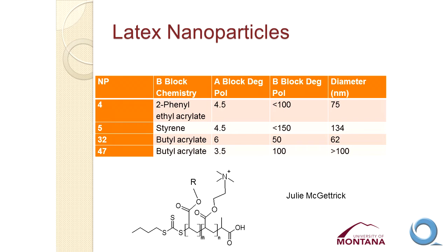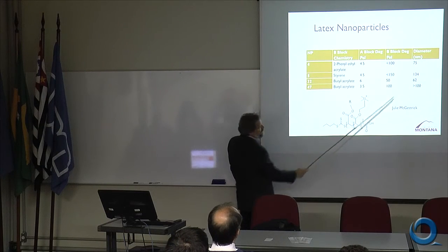All right, I came here with several different nanoparticles that had all been synthesized by Julie. We've evaluated 4 of these. 2 of them have aromatic functionality in the hydrophobic core region. And 2 of them have just butyl acrylate in that hydrophobic core region. The butyl acrylate materials differ in terms of the length of this cationic, the degree of polymerization of the cationic group, and also in the overall size of the nanoparticles.